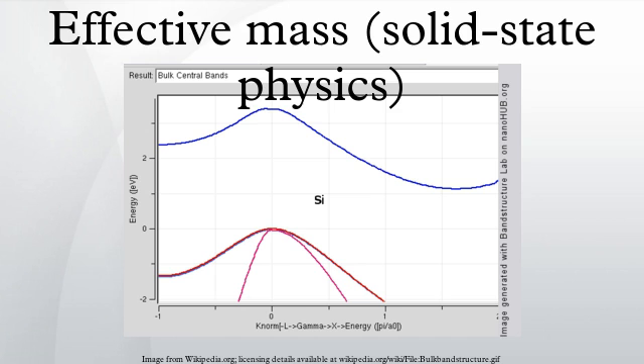Experimental determination. Traditionally effective masses were measured using cyclotron resonance, a method in which microwave absorption of a semiconductor immersed in a magnetic field goes through a sharp peak when the microwave frequency equals the cyclotron frequency. In recent years effective masses have more commonly been determined through measurement of band structures using techniques such as angle-resolved photoemission or, most directly, the de Haas-van Alphen effect.